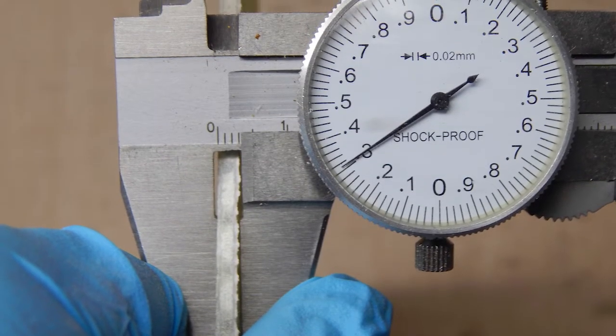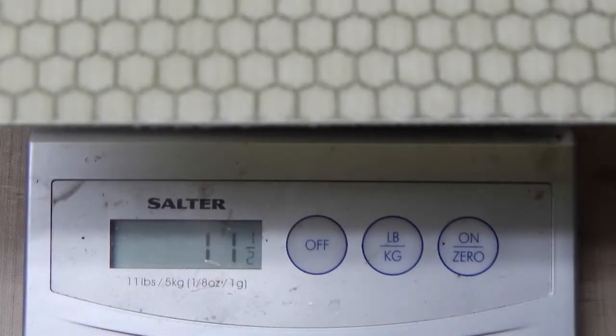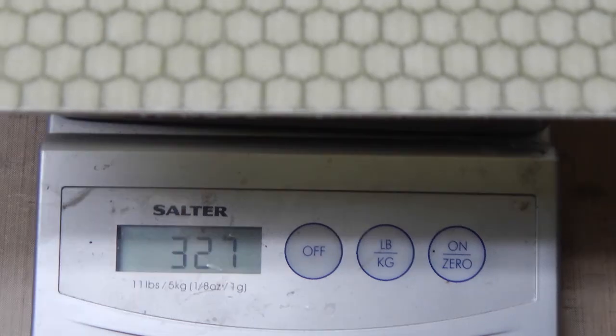Overall a little more than three millimeters thick. And weight wise for one square foot, eleven and a half ounces. And 327 grams per square foot.